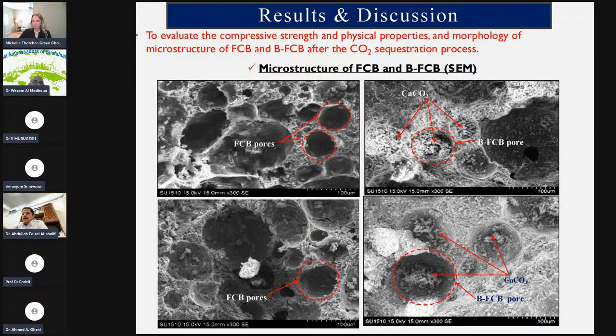Okay, look at the results with bacteria and without bacteria. In the SEM photo without bacteria, the whole porous structure has almost no precipitation of calcium carbonate. But on the other side, the right side, with bacteria, we can see most of the pores, or some of the pores, already healed by self-healing. This is what we call self-healing of the concrete pores.